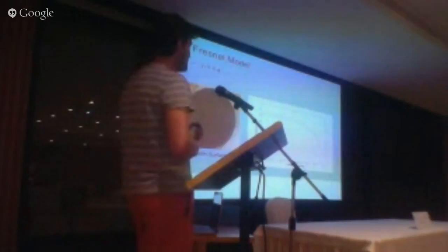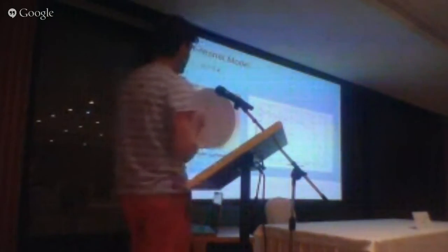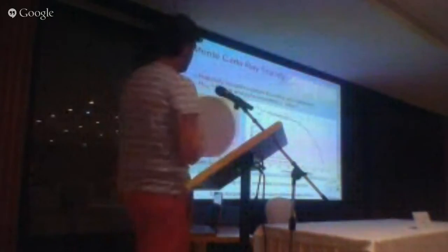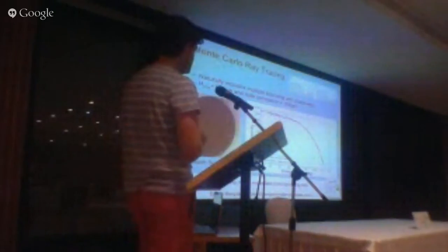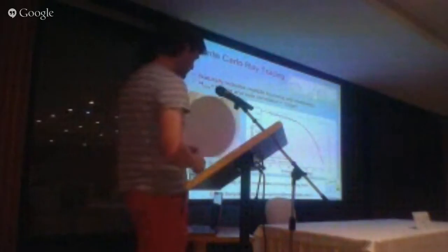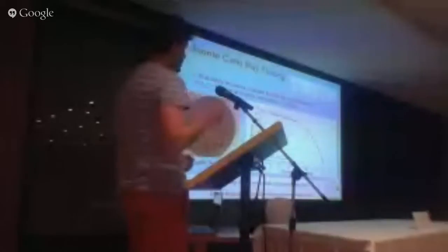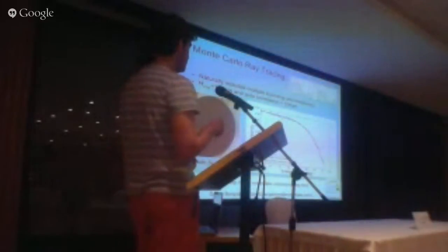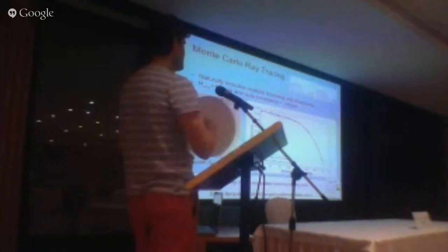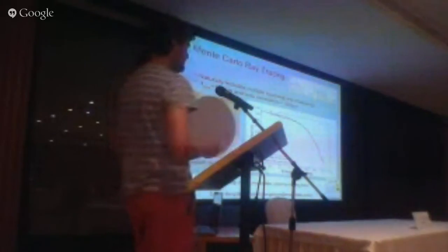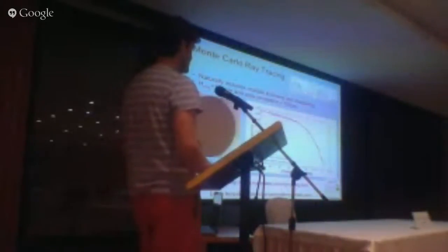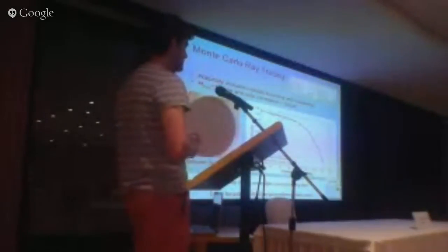Well, all I can say is that for this surface here, the reason I think we're sensitive down to the micron scale is that this surface deviates from a perfect Fresnel-like response, and it appears that if you fit it with a ray tracing approach, where you give it micron scale, 100 micron scale roughness, then you accurately model what you're measuring. So I guess I haven't directly measured influences of surface roughness at the micron level scale on the directional emissivity, but I'm just implying it. So I guess I need to come up with some kind of experiment where we find something that's smooth on the micron level scale and show that that has a perfect Fresnel response. But that would be tricky. Sorry, that's not a great answer.